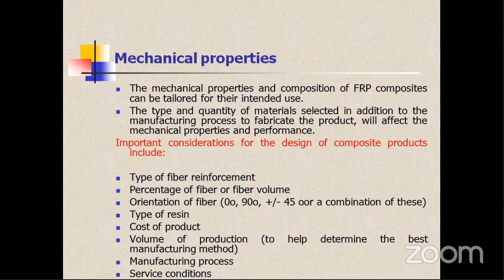You should be very, very careful about what design considerations you should account for when you go for selection of fibrous reinforcement. First, you should know the type of fiber reinforcement, whether it is carbon fiber or glass fiber, and how much percentage of fiber or volume. That is very, very important. You cannot go for 100%. It should be, as I said earlier, 60% maximum if you use hand layup, or you can think of pultrusion or filament winding, where up to 80% fiber you can impregnate with the polymer for the development of the products.